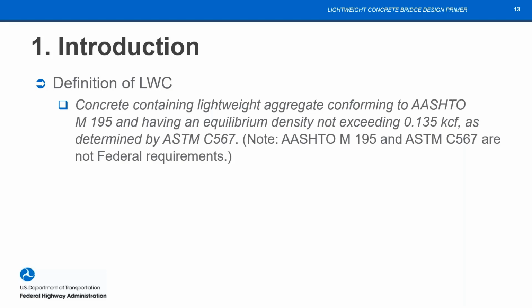The term equilibrium density is maybe not familiar to some folks. The definition in ASTM is that it's the density of structural lightweight concrete after exposure to relative humidity of 50% and a temperature of 23 degrees C, room temperature, for a period of time sufficient to reach constant mass. And what it's talking about there is that lightweight concrete typically has some excess water in it because of the water that had been absorbed into the aggregate before batching, and that some of that moisture isn't tied up in hydration products, and as a result can move out of the concrete.